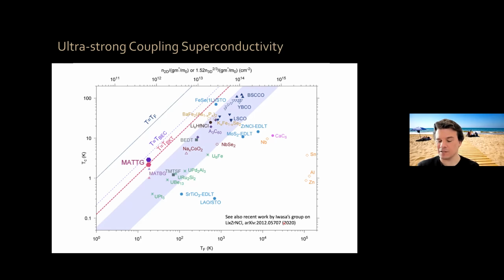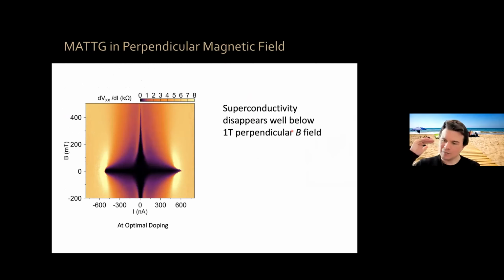So, when we measure magic angle twisted trilayer graphene in a perpendicular magnetic field, we see that superconductivity is suppressed due to orbital effects. And that happens well below 1 Tesla perpendicular magnetic field, okay? Now, because this system is a 2-dimensional superconductor, if you apply an in-plane magnetic field, you don't have the typical orbital effect, you don't create vortices. So it's interesting to see what's limiting the superconductivity with an in-plane magnetic field, okay?